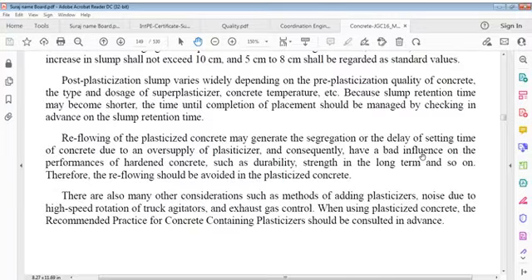Post-plasticization, slump varies widely depending on pre-plasticization quality of concrete, type and doses of plasticizers, concrete temperature. Because slump retention time may become shorter, time until completion of placement shall be managed by checking in advance. Reflowing of plasticized concrete may generate segregation or delay of setting time of concrete due to an oversupply of plasticizer and consequently having bad influence on performance of hardened concrete such as durability, strength in long term and so on. Therefore, reflowing should be avoided in plasticized concrete.